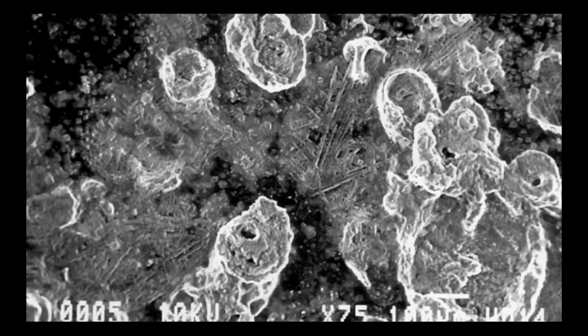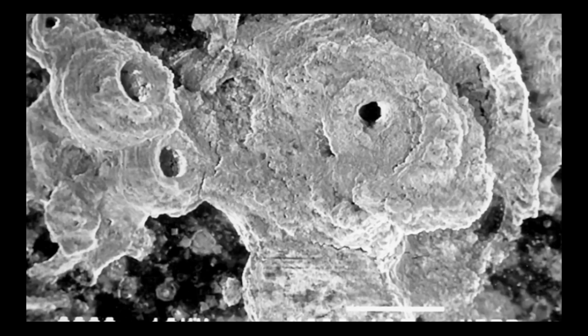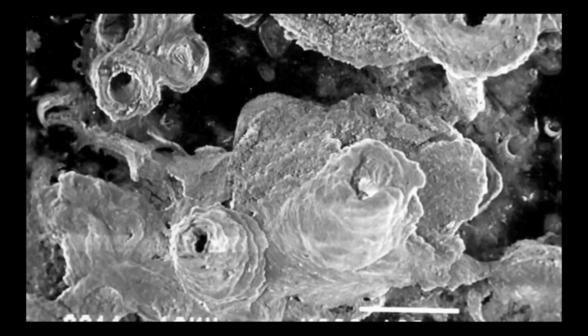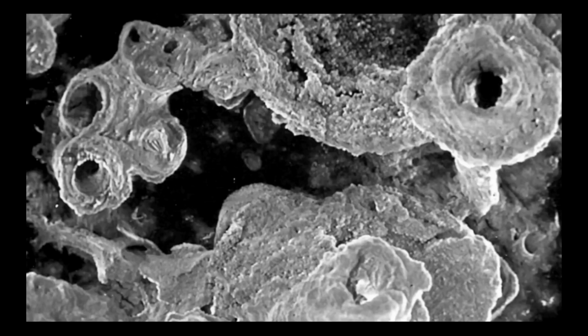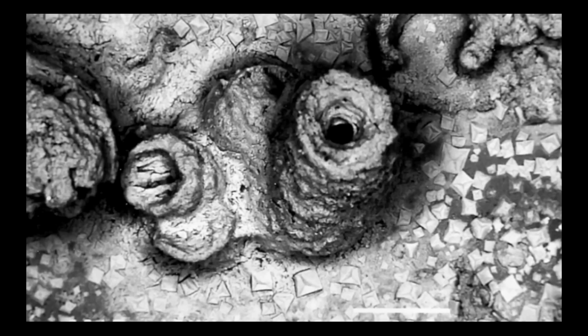In the electron microscope, the white corrosion product on the surface of the corroded aluminum now develops certain features. We can see that now there are mounds and tubes and chimneys poking off the surface. These are the chimneys we described earlier, where the hydrogen bubbles pump the aluminum out, and it reacts with the water to form aluminum hydroxide. This mound here looks like a perfect smokestack. It's such a straight chimney. And off to the side of it, we can see little cubic salt crystals.